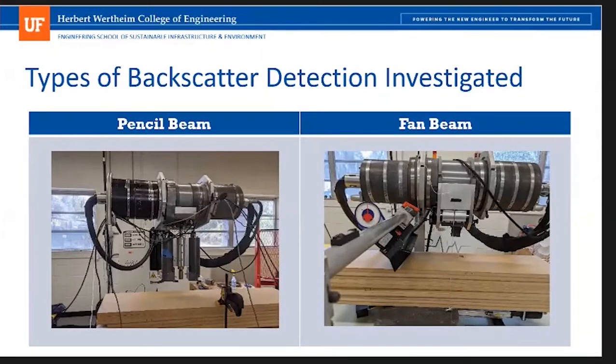It's very powerful in the sense that you get very good resolution. The system can do millimeter to sub-millimeter resolution, but it does compromise speed as you're doing one pixel at a time, looking at a pixel every half to 1 second. It can obviously take a lot of time even just to scan one crosstie. But it's used for us as a proof of concept.